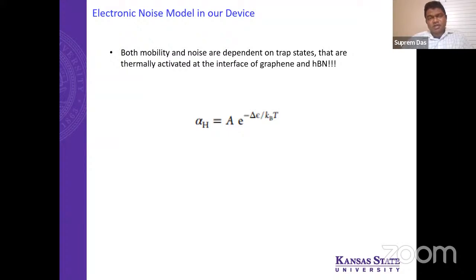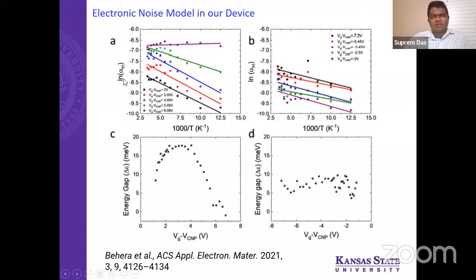So to understand the trap states, now we also need to know how this trap energy, delta E, is dependent on temperature. So we have a model that your trap states can be modulated with temperature with this type of behavior. Typical behavior is exponential of minus energy divided by kT. So by taking that, and again from our experimental data, this is your log alpha versus 1 over T.